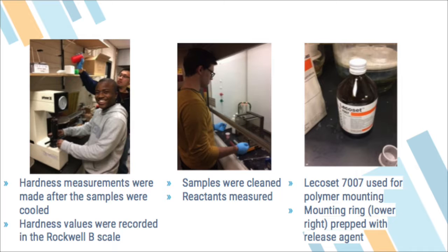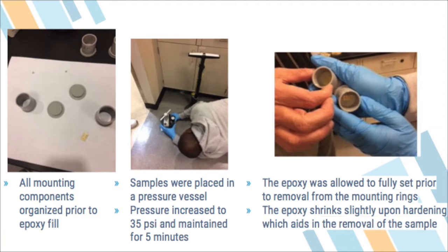The proper amounts of Lecoset and binary reactants were weighed to ensure a quality polymer set that would be suitable for further processing. Mold rings were capped and sprayed with a Teflon release agent. A final check was performed of all components prior to the mixing of the polymer reactants. This was to ensure that everything was ready, as the epoxy has a relatively short working time. The components were finally assembled with the metal samples in the bottom of each mounting ring. The epoxy was then mixed and carefully poured into the mounting rings.